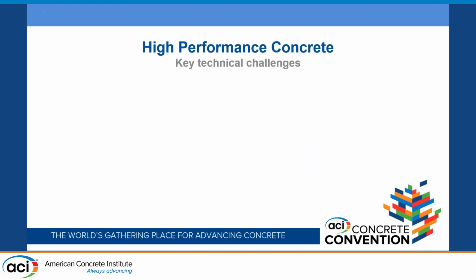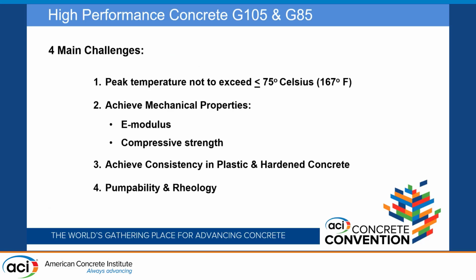Okay, so some key technical challenges for the high performance concrete. There were 4 main technical challenges. We're going to focus on challenges 2 and 4 on this slide, but it's also important to discuss the thermal challenges briefly. The thermal plan indicated that the mass concrete for the mass elements on this project, the core wall and the mega columns, needed to be below 167 degrees max because of the sheer mass size of those placements. To achieve this, hot block trials were conducted to confirm the peak temperature was less than 167.